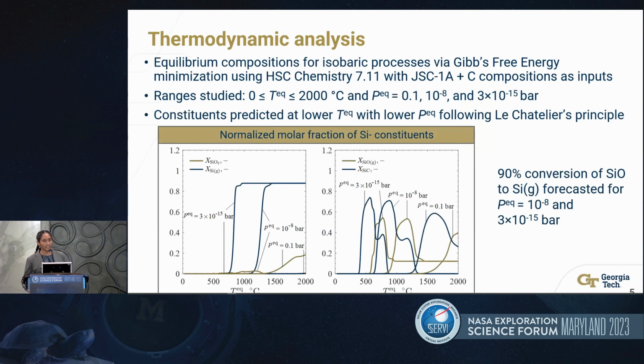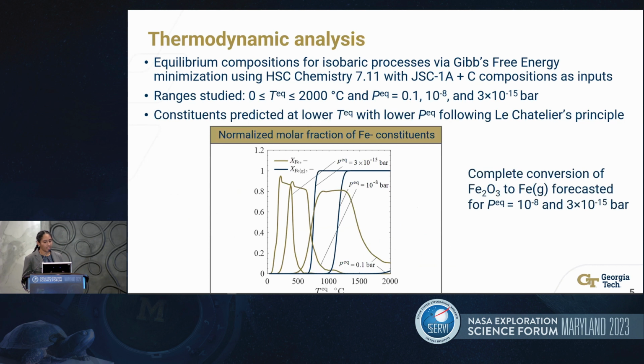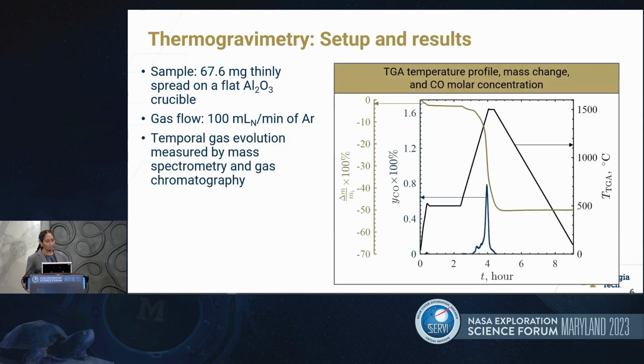Results show that constituents were predicted at lower temperatures with lower pressures, following Le Chatelier's principle. In this case, silicon monoxide and silicon carbide were considered because they are stable intermediates in silicon production. About 90% conversion of silicon monoxide to silicon gas was predicted at 10^-8 bar and lunar surface pressure. This means that complete conversion was not predicted within this temperature range. However, complete conversion of iron oxide to iron gas was predicted at 10^-8 bar and lunar surface pressure.